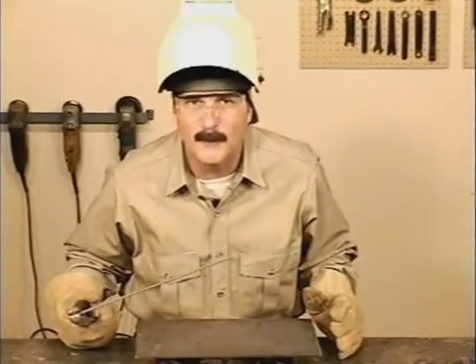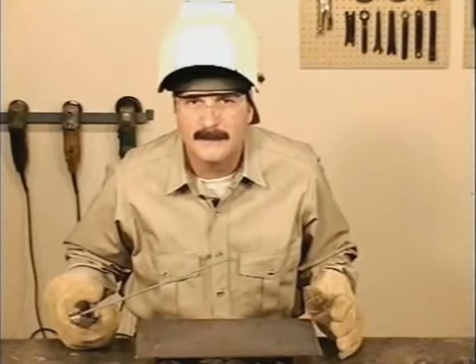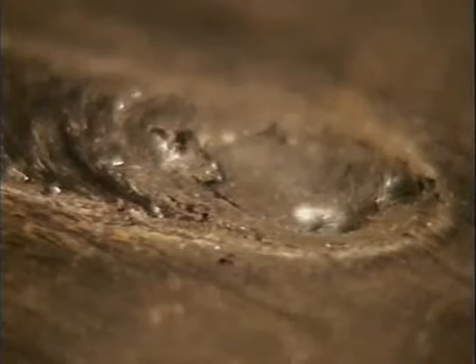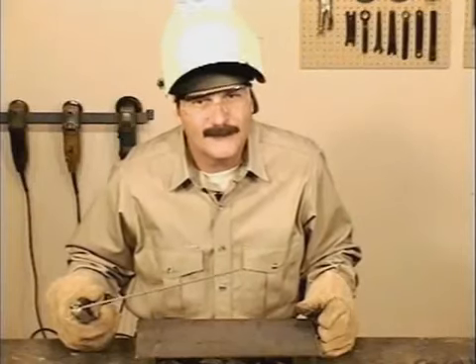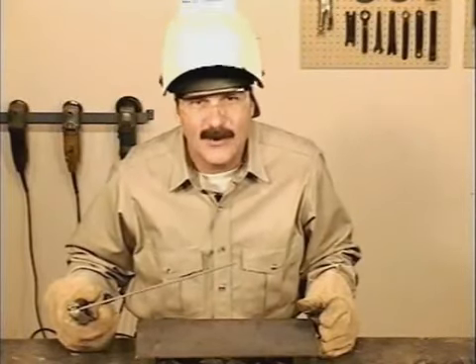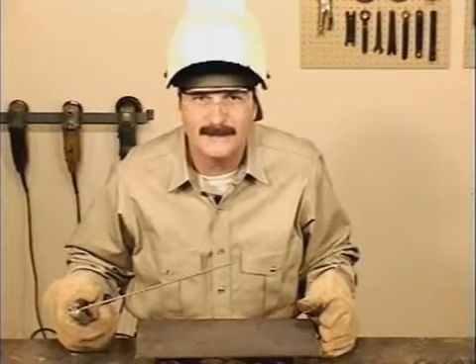As you gain more control of the rod, try using a slightly higher amperage setting and increasing the speed of travel. The higher amperage setting provides better penetration and a smoother finished weld bead. Try to weld as hot as you can control the molten puddle. To finish a weld bead, add a little extra metal before you pull out, to avoid leaving a crater that's below flush with the surface of the base metal. Circle the rod once or twice, then bring the rod up and back over the weld. While different rods may not look quite the same, these are the basic steps for all the welding rods. Scratch to get the arc going.